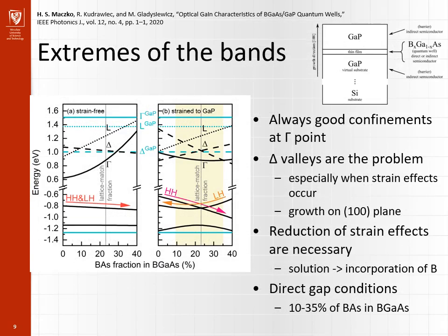Blue lines on the charts present the band extremes of gallium phosphide and black lines of the boron-gallium arsenide. It is visible that this system is described with type 1 band offset in a very wide fraction range because gallium phosphide has a much wider direct band gap than gallium arsenide does. Therefore, conditions are favorable for confining electrons and holes around the gamma point of the first Brillouin zone in boron-gallium arsenide alloys.